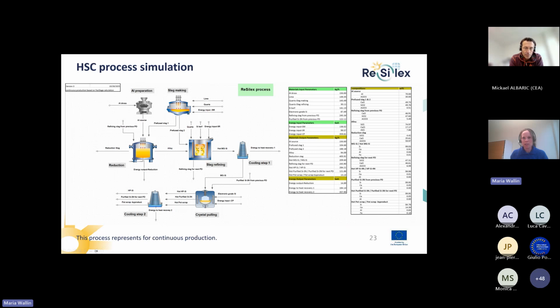Here we also in this project have simulated the process in FactSage. We're doing LCA on this. And you can see here that this is the second round production based on the FactSage calculations and also on the results that we have from the process. So this is a continuous process. And what we do is that the refining slag from the first round and the pot scrap and purified 3N silicon, the bottom of the ingot, is recycled back. And the pot scrap is taken out so that we get to sell that as a product, so that we get a purer and purer process in the end and get rid of some impurities. And these are also valuable products in the market.